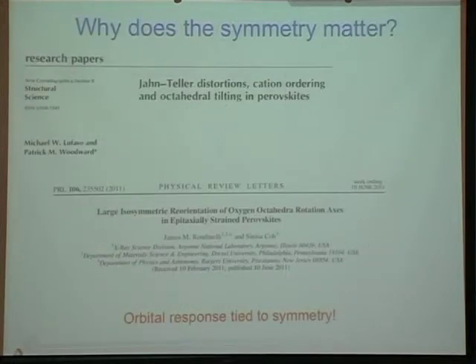You care because symmetry is extremely important. It turns out that a rhombohedral space group does not allow a Jahn-Teller distortion. So in order to impose a Jahn-Teller distortion on a rhombohedral material, you have to drastically lower the symmetry. But that, of course, means energy, because you're going to have to pay all of that strain cost to do it. Whereas orthorhombic allows a Jahn-Teller distortion. So what we found was that the knowledge of the bulk materials and how symmetries connect to orbital polarization is actually extremely important because it's still very relevant in these films. And so you can now use this as a design rule.